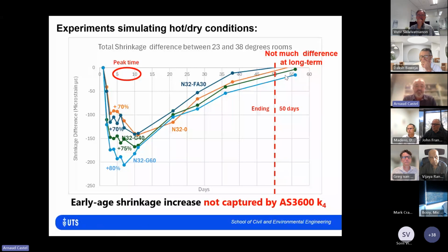So the conclusion of this test, and it's consistent with the results we have with the 25 MPa or 60 MPa concrete, basically the same: the K4 coefficient in the standard is not able to capture at all the effect of that increase in water evaporation rate that will happen in the field just because it's a hot climate and a dry climate. That's not possible to do with the standard. The K4, as I said, is for long-term estimation of shrinkage, and the results are consistent in that case, because at long term there's really a marginal difference between the two conditions.